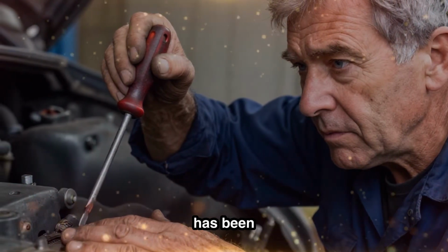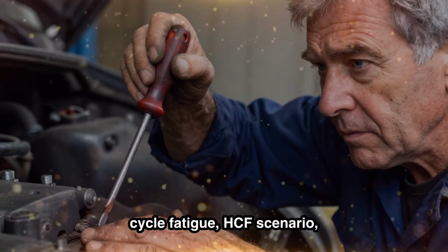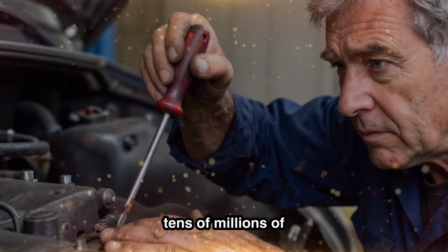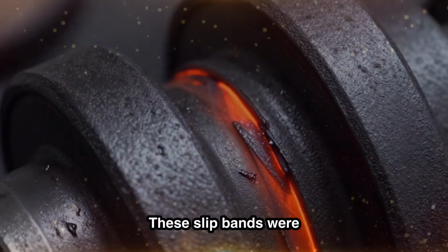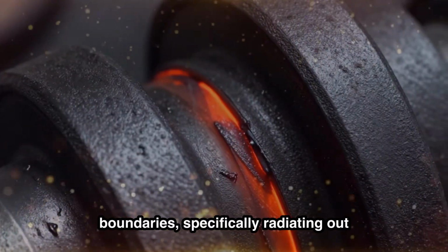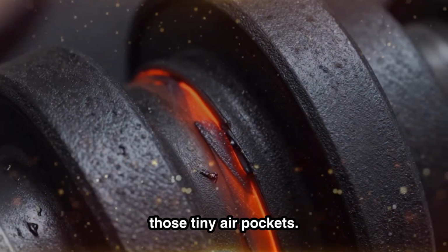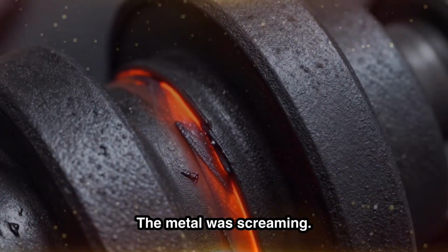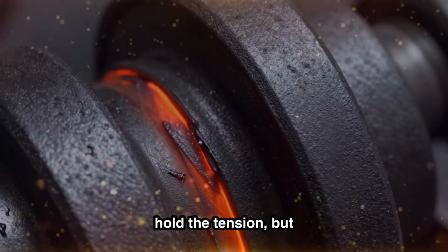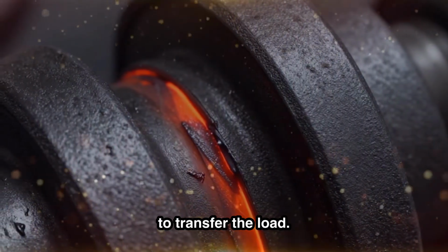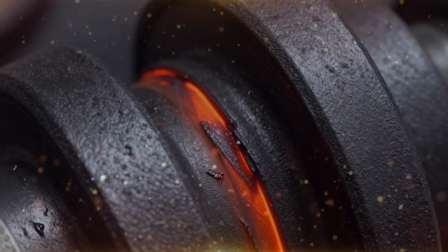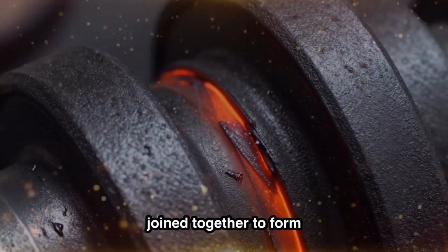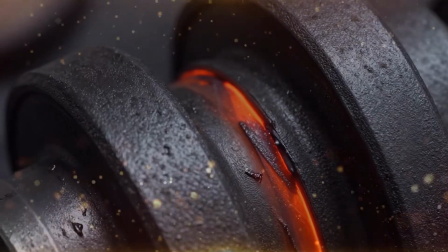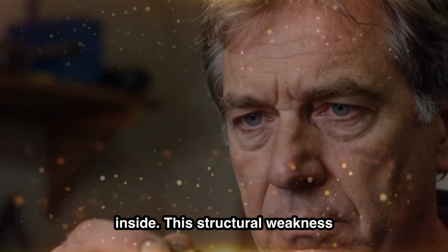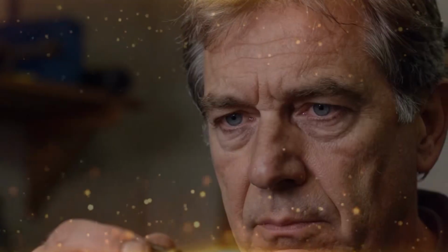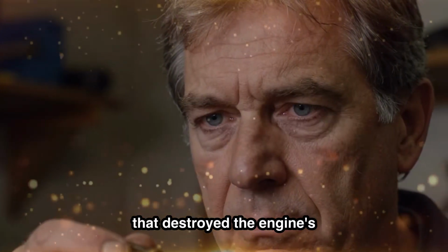They appear when the metal has been pushed past its yield strength in a high cycle fatigue, HCF, scenario, tens of millions of load cycles. These slip bands were clustered around the grain boundaries, specifically radiating out from those tiny air pockets. The metal was screaming. It was trying to hold the tension, but the porous structure gave it nowhere to transfer the load. The slip bands turned into micro cracks, and those micro cracks joined together to form a fracture that was invisible from the outside, but fatal on the inside. This structural weakness is what allowed the arm to bounce, creating that harmonic chatter that destroyed the engine's main bearings.